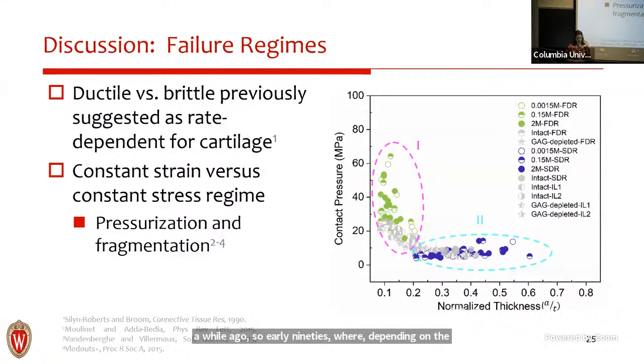The other thing that we think we're seeing in this is that there's some pressurization and fragmentation. So if we add our line versus star cracks on these two cases, our first case, regime 1, is usually the line-shaped cracks, and regime 2 is usually the star-shaped cracks. Those star-shaped, or 3-branch cracks, may be consistent with this idea of a pressurization and a rupture.